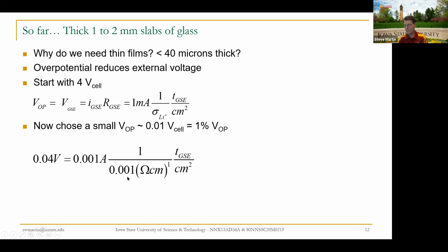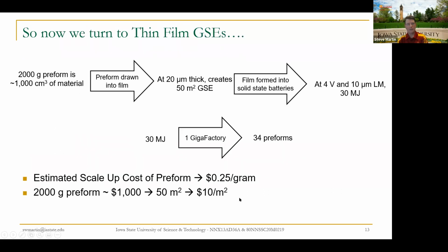We have our conductivity of these things, about 10 to the minus 3, 0.001. And you can do the simple math, and in order to get such a small overpotential, you get about 40 microns. And so that's why we need very thin films. And that's where our glass comes in, where we can pull the glass into a very thin film. We can stretch it just like taffy.